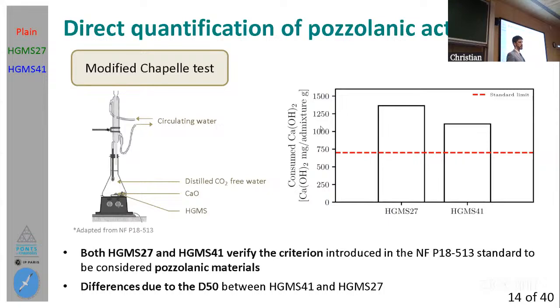We can try to confirm this with the modified Chapelle test that I have performed, and there, just to understand it, we know that this modified Chapelle test is a direct quantification of the pozzolanic activity in which we expose these spheres to a solution that has an abundance of calcium hydroxide, and we are able to measure the direct consumption of this compound in particular conditions of high temperature. With the corresponding standard established limits indicated by this red line here, we are able to see that both spheres presented higher consumption than that established in the standard. This means that according to this standard, both spheres could be considered pozzolanic materials, and moreover, HGMS27 presents higher values than HGMS41, which relates to a higher pozzolanic activity of HGMS27 than 41, possibly due to the smaller particle size of that sphere, of 30 micrometers in mean particle size.